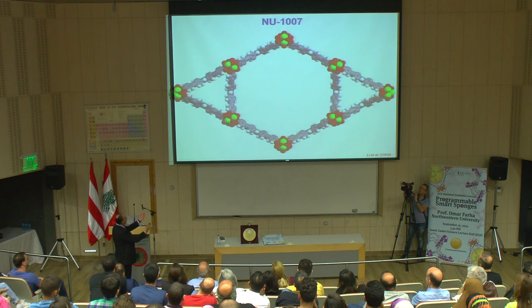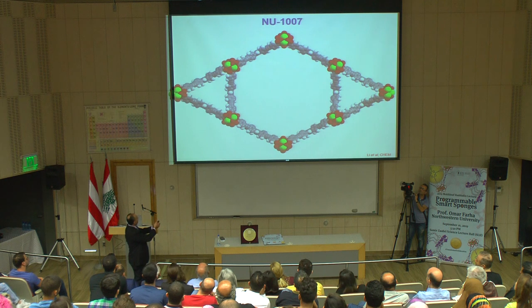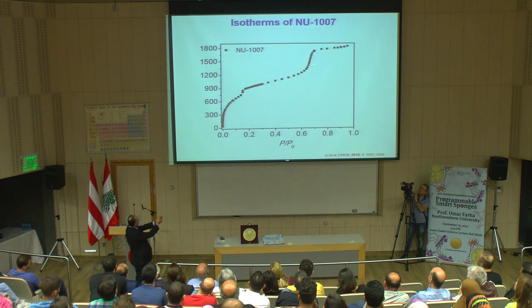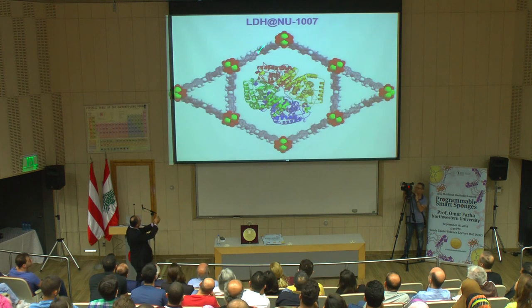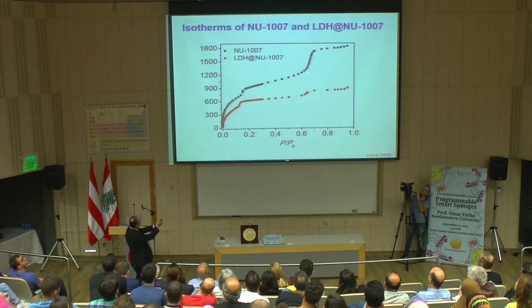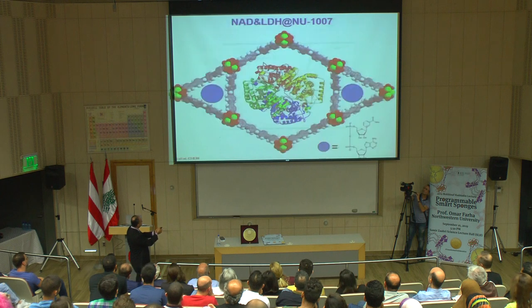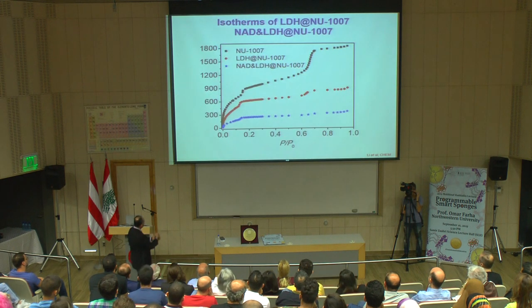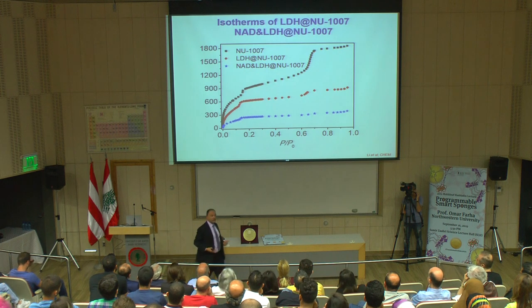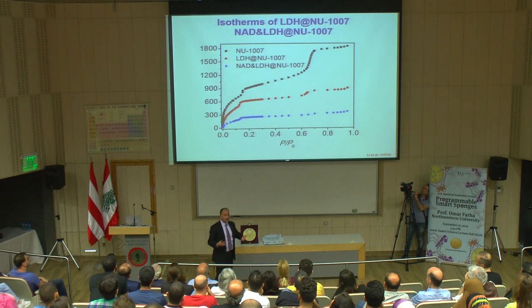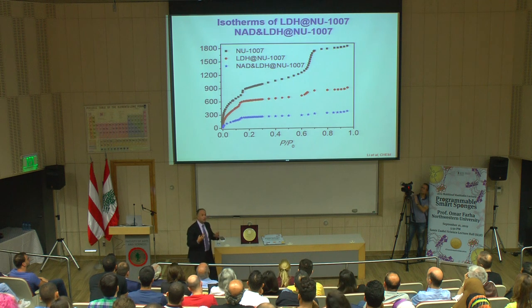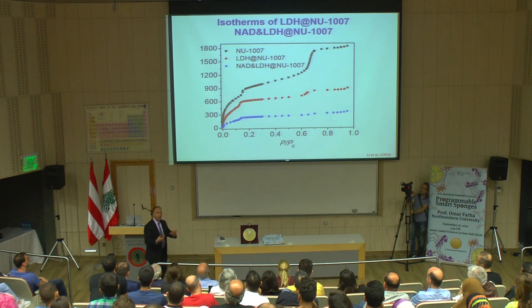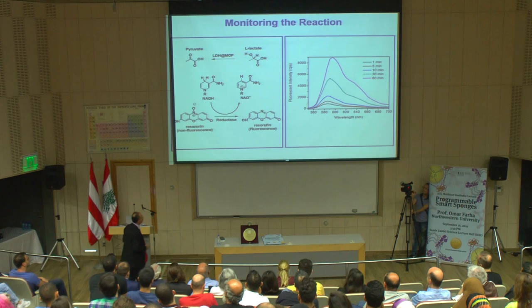Now we got to test our largest one, the 7 nanometer. This is the nitrogen isotherm. If you put the enzyme in the large channel, you could see the reduction only happened from the hexagonal channel. And if you put the cofactor in the triangle, you could see the reduction happens in that triangle. So this is indirect evidence that the two channels really work together, and you need both channels.